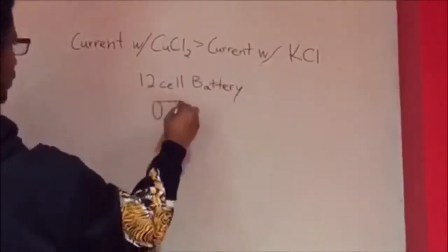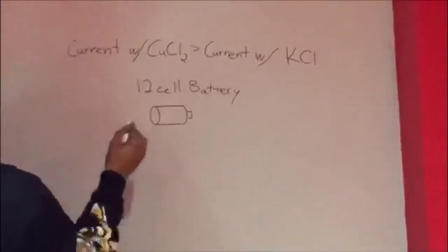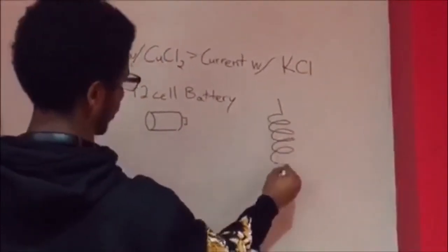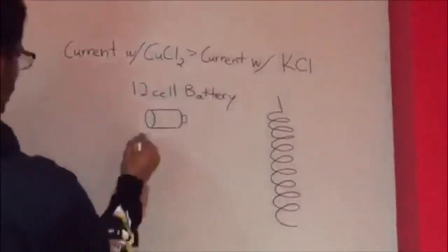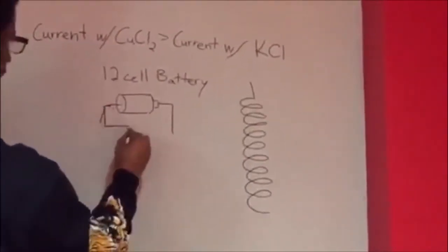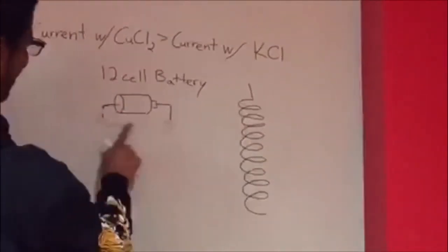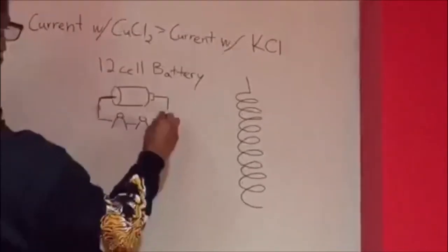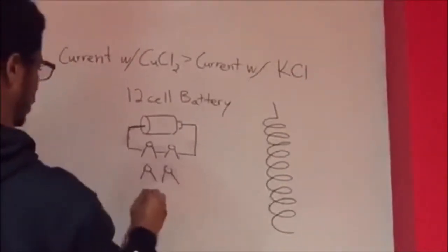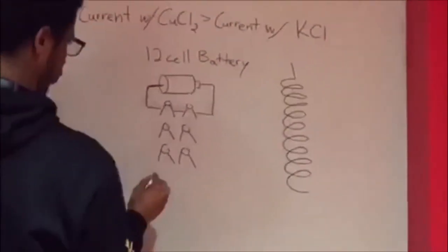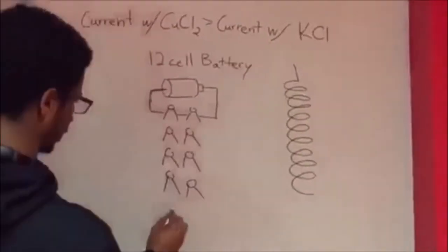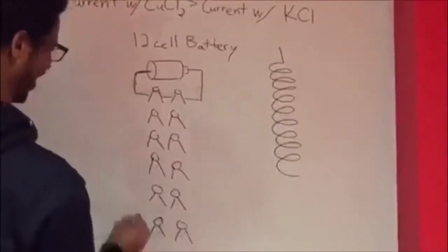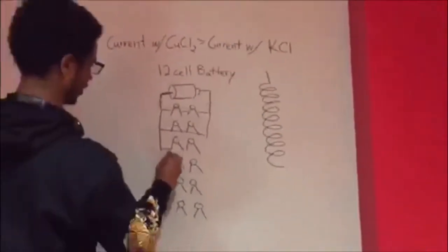After choosing copper chloride as the electrolyte for our cells, we were now ready to assemble our battery and test. We connected all 12 cells in series, with each containing a wire of aluminum and a wire of copper, both coiled in 10 loops to try and fit as much surface area of metal and electrolyte in each cell as possible, while maintaining consistency from one cell to another. We dissolved our copper chloride salt and poured it into each of the 12 cells. Then we connected our 12-cell battery to our multimeter and circuit.